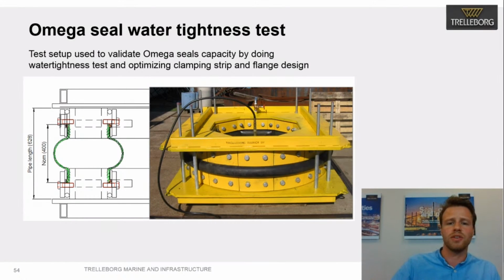So those omega seals are sometimes tested as well, especially when you create a special type of omega seal. This is a type of construction you can use for that. You basically place 2 omega seals next to each other, and you raise the pressure within those omega seals to check where the failure mechanism is and to check how the clamping system behaves over time.